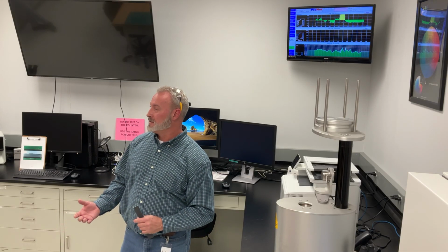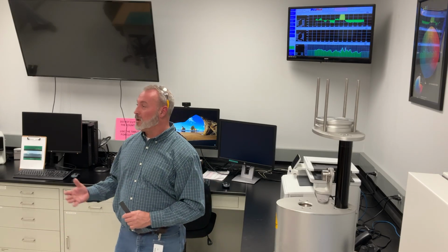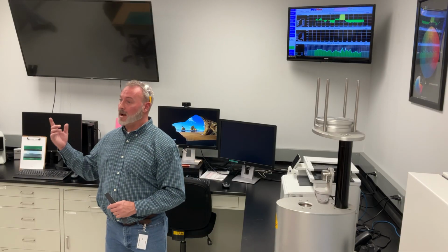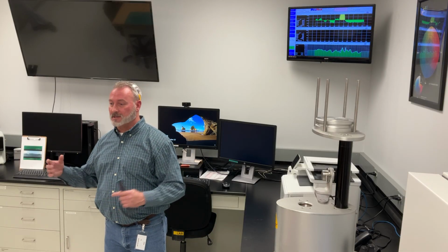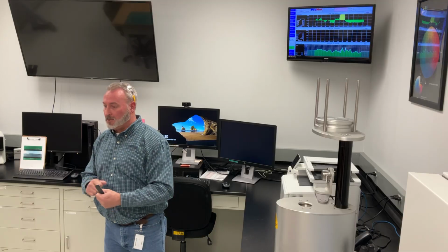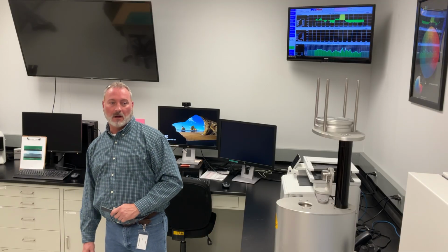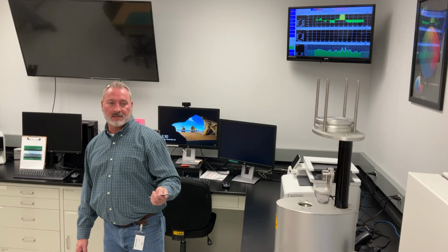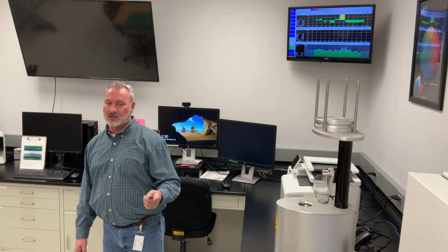than 0.5% or shrink. If it grows or shrinks more than that, what happens on the roof when it goes through the freeze-thaw cycle, it's going to possibly pull away or pull at those seams, right? That's a pretty stable test. We very rarely have any issue with that.